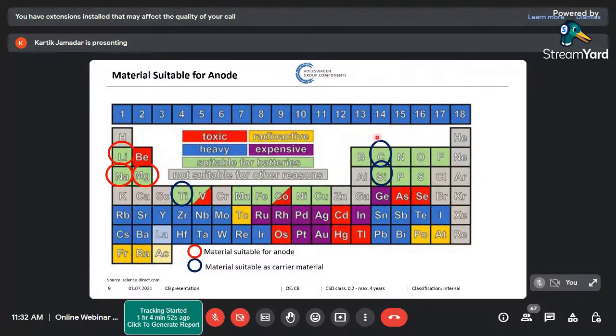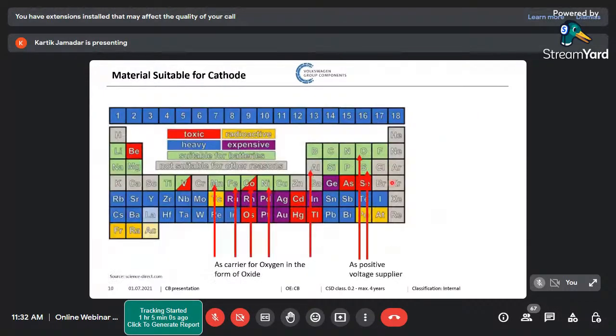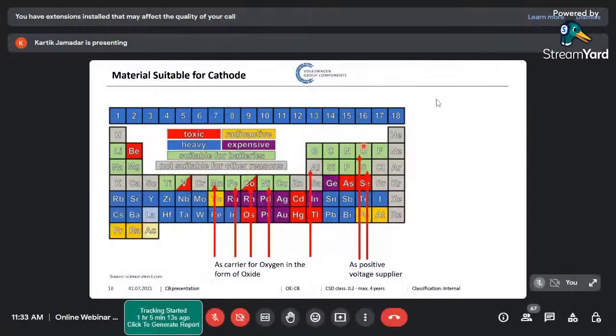But for the EV vehicles, normally we would use either carbon or carbon in the form of graphite, or maybe replace it with some kind of silicon. What about the cathode side? On the cathode side, I told you we have a very important part, oxygen. It would be wonderful to have only oxygen without this metal oxide, but the oxygen alone cannot help you because it forms an irreversible compound called lithium oxide.